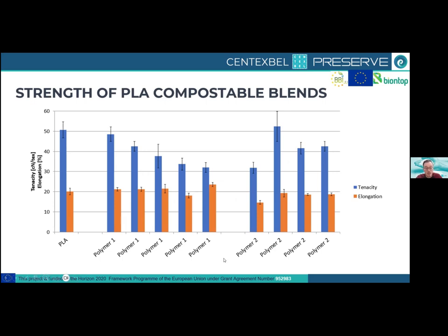When we blend this together with polymer 1, as I said, confidential information, I cannot give the type of polymer itself, but you can see here the difference is the percentage of polymer that we blend into the PLA. The left one is with the least amount of polymer 1. The right one is with the most amount of polymer. When adding only a little bit of that polymer, there is no statistical difference in the strength of this material. But when we add more and more of polymer 1 into this blend, the strength of this material gets lower and lower. But it is still above 30 centinewton per tex, around 35 we wanted to reach with this TPEC. So this is pretty good.